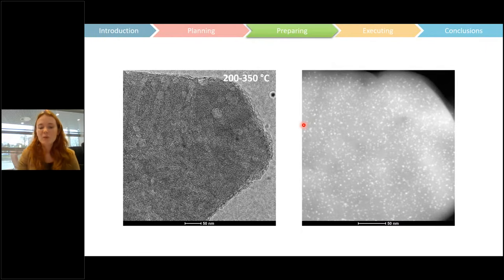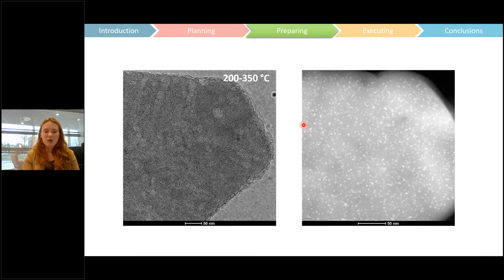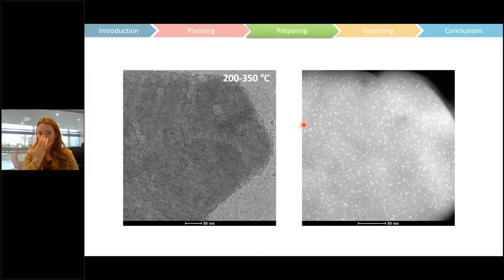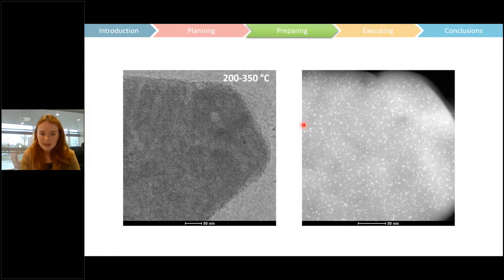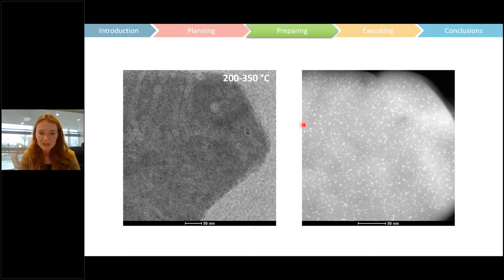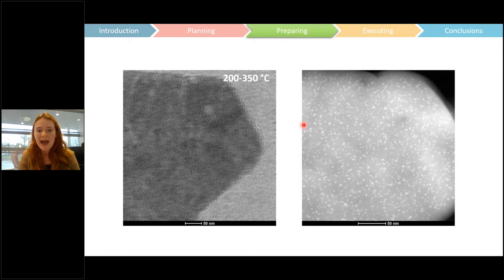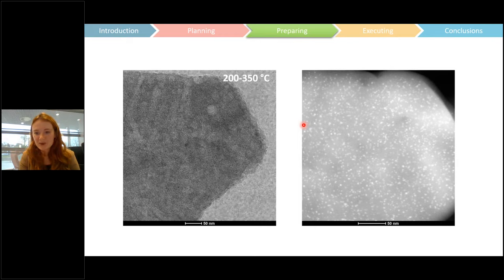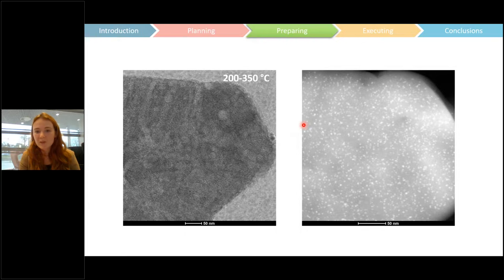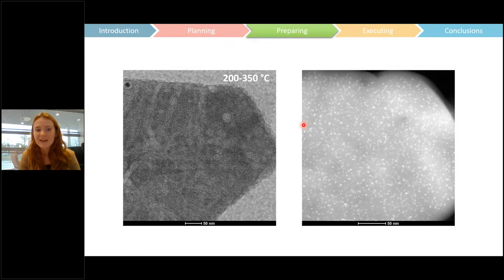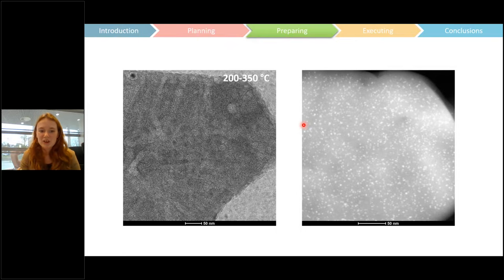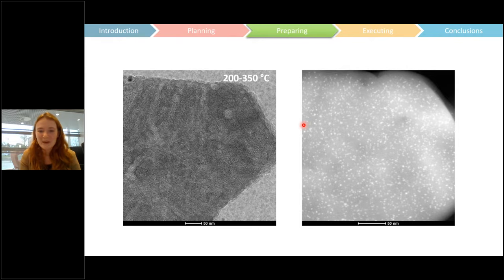Here you can see an example on the left of an experiment I did in situ on a zeolite sample. In TEM mode, I thought it was the best mode for this particular sample, and it wasn't, because once I switched to STEM mode, on the right you can see we have loads of platinum nanoparticles that have grown everywhere. And sometimes you just don't know until you run your experiment what's going to be the best option. So sometimes you do end up repeating just purely because you follow your instincts and it does just go wrong in the end.